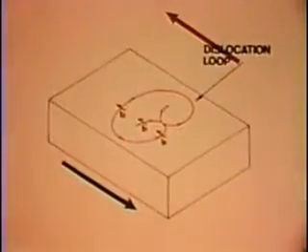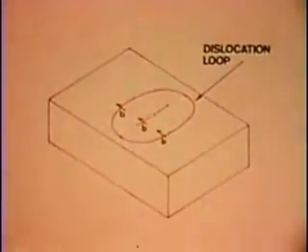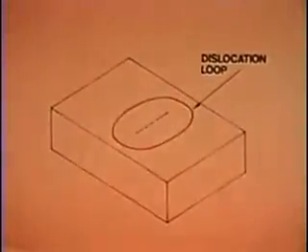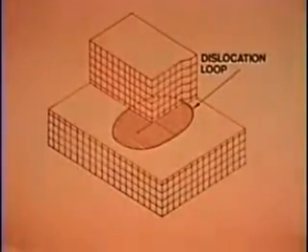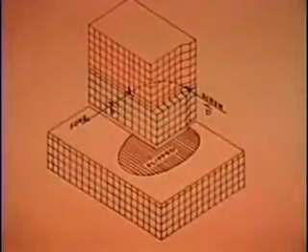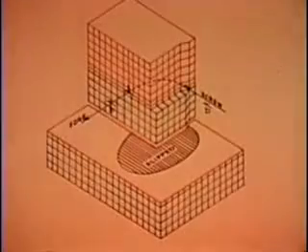In the insert, these segments are assigned the same direction, so their Burger's vectors are opposite. Their consequent annihilation pinches off an independent loop from the segment attached to the pinning points. The region inside the loop has slipped, that outside has not.